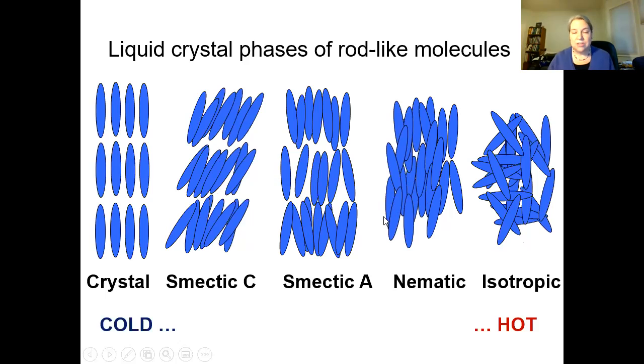And what's the most interesting piece of physics about this is that the degree of orientational order in a nematic is defined by a scalar order parameter that tells us how well aligned the molecules are. If you heat them through the phase transition, they go from essentially fully ordered to fully disordered. But in between, the quality of the order changes. And so the scalar order parameter is actually a function of temperature. And that is the key handle we have to make liquid crystal polymers actuate.